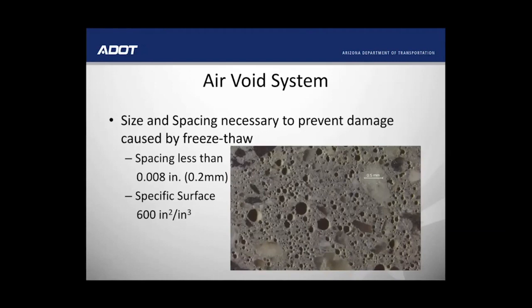It turns out that as we are adding additional supplementary cementitious materials such as fly ash, included at 20%, and silica fume, included at what percent? Yep, about 5%. By densifying the mixture, we are decreasing the permeability by such an extent that the hardened air void properties may be less vital to achieving freeze-thaw durability.